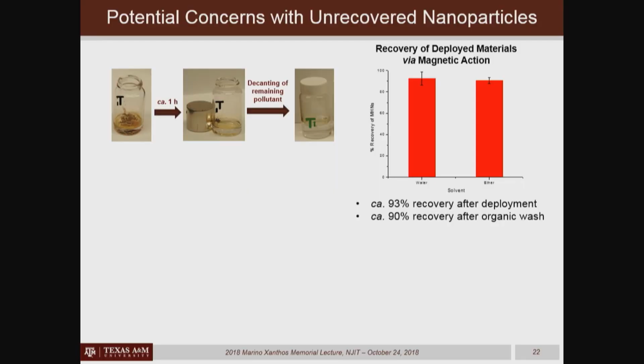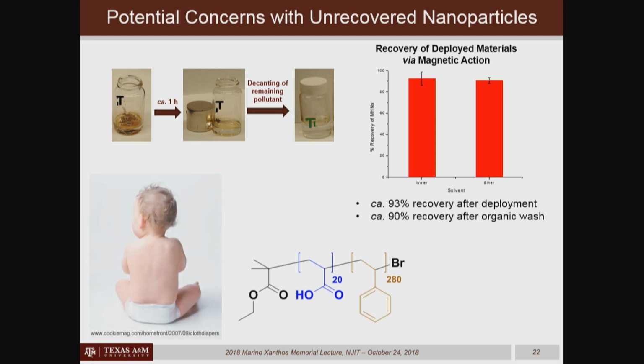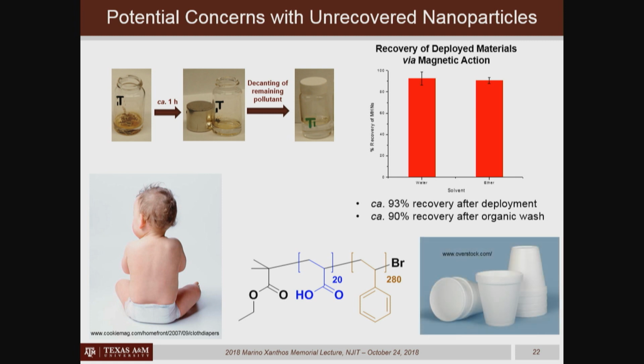Okay, so I've made these materials sound like they're really great, right? So now we have to get into, what's the problem, right? And we come back to this block polymer structure that's used to assemble into these materials. And as I said, it's comprised of polyacrylic acid connected to polystyrene. And I mentioned that polystyrene is styrofoam. I didn't mention that polyacrylic acid is actually the super absorbent hydrogel material in baby diapers, so considered to be safe. Styrofoam is considered to be safe, but the problem with both of these is that they're persistent in the environment. They don't undergo breakdown. They're also petrochemically sourced in terms of the monomer building blocks from which they're produced.